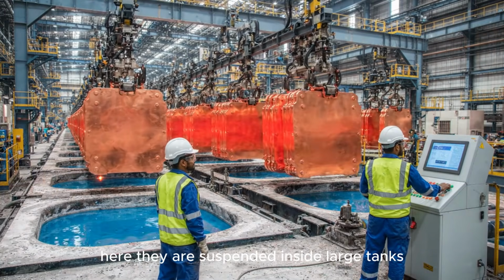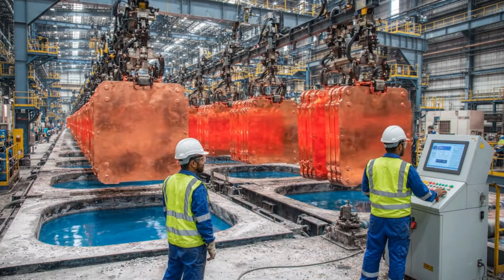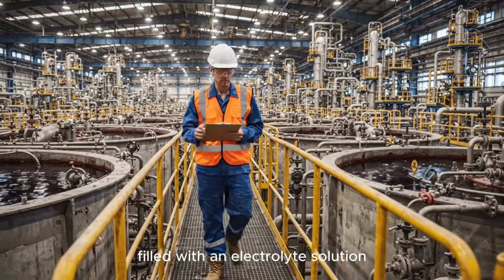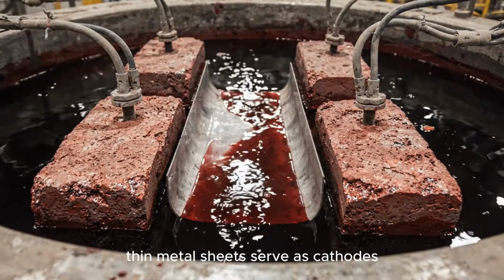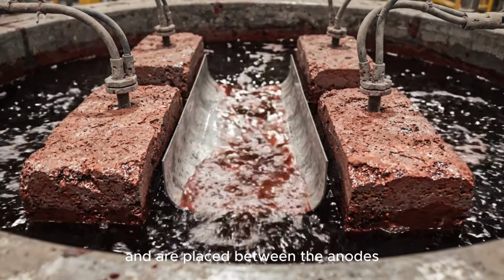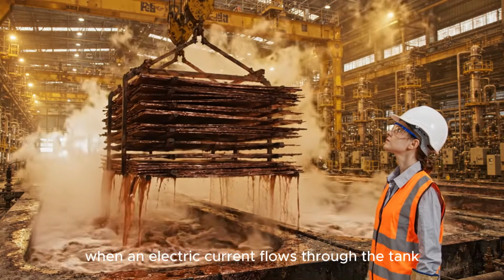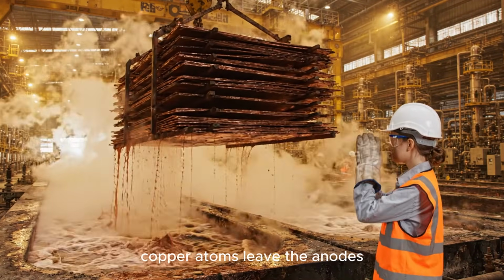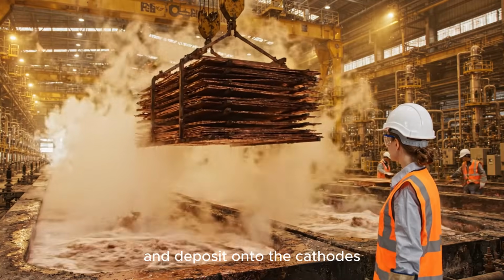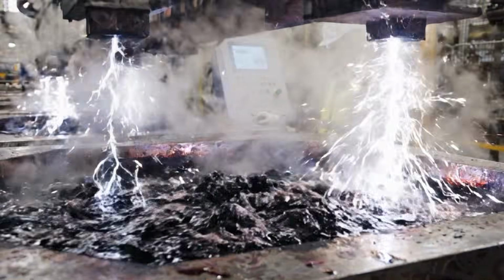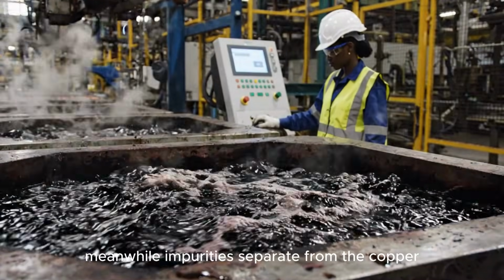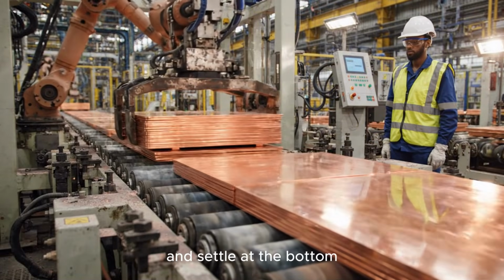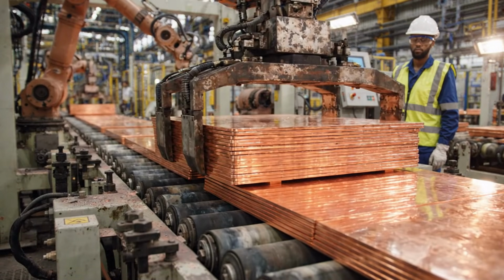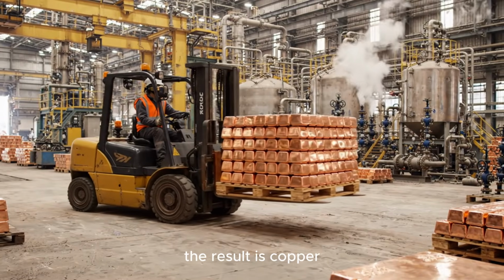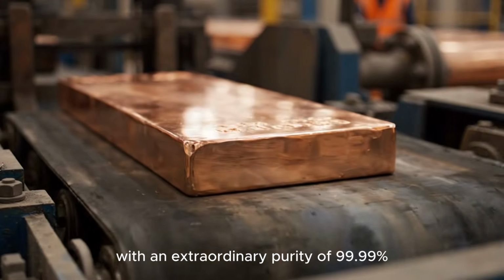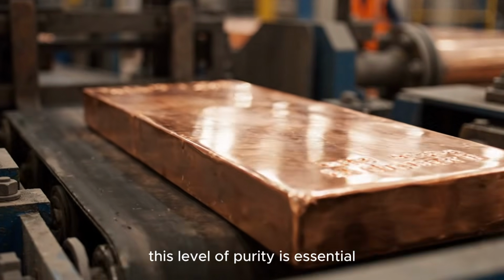Here, they are suspended inside large tanks filled with an electrolyte solution. Thin metal sheets serve as cathodes and are placed between the anodes. When an electric current flows through the tank, copper atoms leave the anodes and deposit onto the cathodes. Meanwhile, impurities separate from the copper and settle at the bottom. The result is copper with an extraordinary purity of 99.99%. This level of purity is essential.